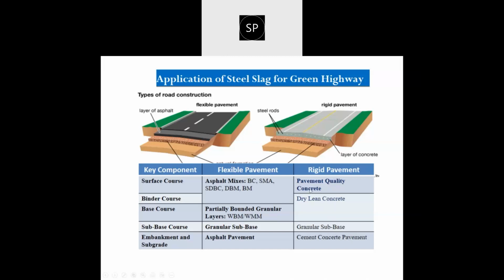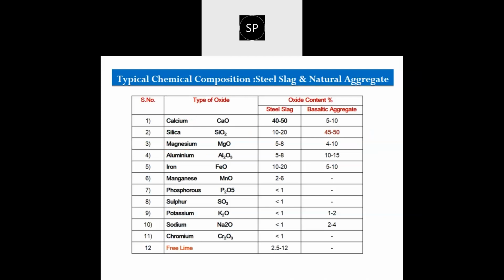And we are utilizing this electric arc furnace steel slag aggregate on Mumbai Goa Expressway on NH-66 near Dolvi, and constructing this rigid concrete pavement using steel slag aggregate as a 100% substitute of natural aggregate.